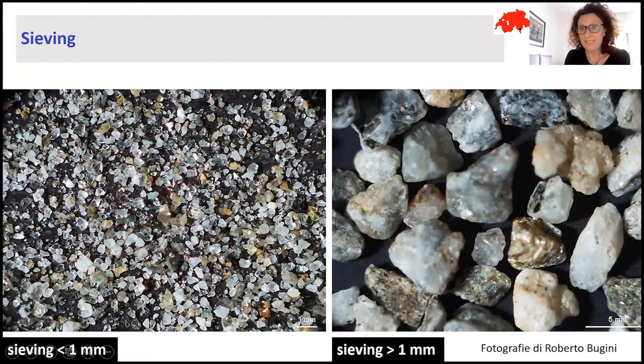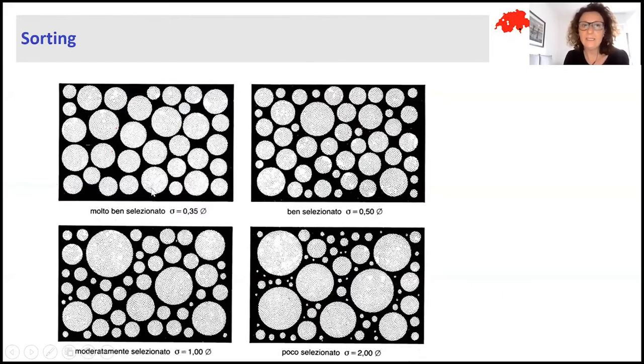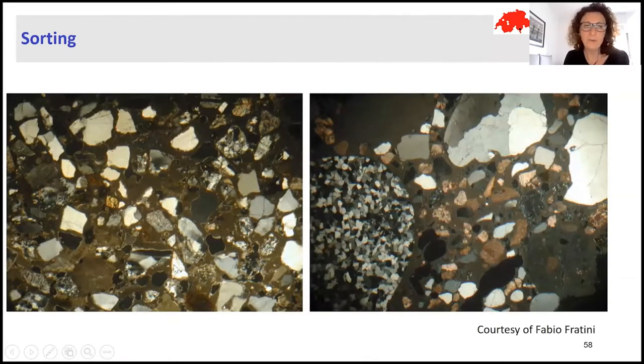The aggregate can be used as it is, or it can also be sieved, selecting a special grain size for the production of mortar. For example, for the production of stucco, the finishing layer was made with a finer particle size of the aggregate, and normally this is also done for the plaster, for preparing a material to be painted on. The aggregate can also be classified as having a good sorting or a poor sorting. Here, for example, you can see a mortar with good sorting, in which the dimension of the aggregate is well distributed, and another type in which we can observe poor sorting, with very fine particles or very large ones.